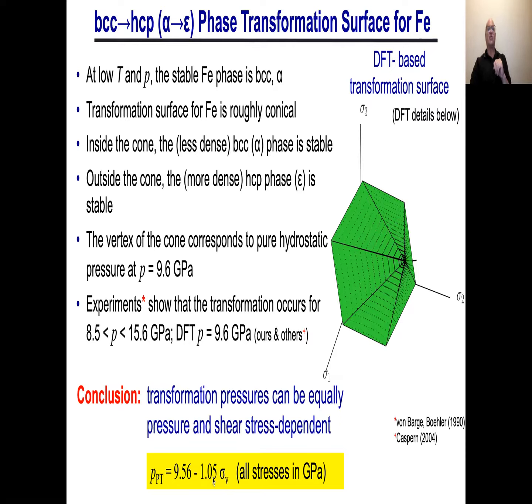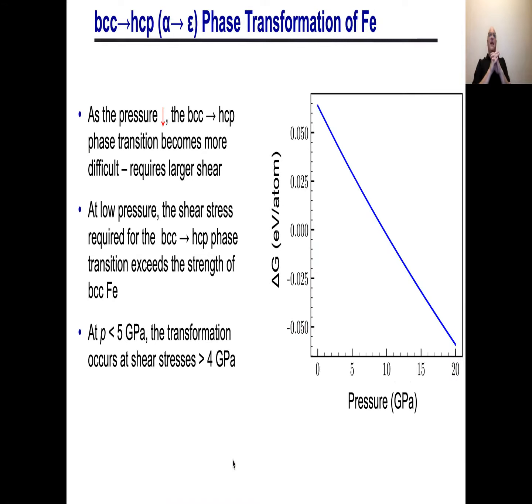So shear stresses really do matter and they affect the transformation pressures. So if I look over at the experimental data where you go from 8.5 to 15.6, it makes sense that's corresponding to different von Mises or shear stresses here. And so since their coefficient is 1, it should be a similar size. Okay, now, first,